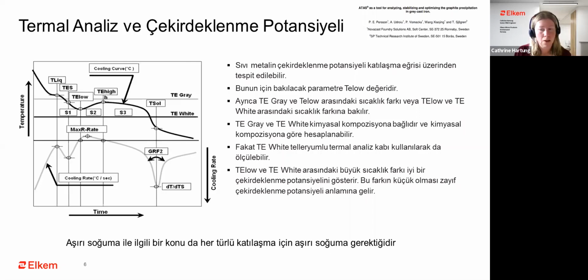So the nucleation potential can most easily be measured versus the TE white in a foundry. And then a large temperature difference between TE low and TE white means a good nucleation potential, while a low temperature difference means a poor nucleation potential. This means fewer possible nucleation substrates for the graphite to grow on. Next.